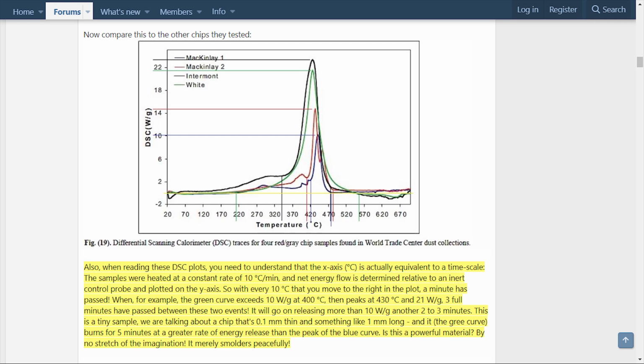So with every 10 C that you move to the right in the plot, a minute has passed. When, for example, the green curve exceeds 10 watts per gram at 400 C, then peaks at 430 C and 21 watts per gram, 3 full minutes have passed between these two events. It will go on releasing more than 10 watts per gram another 2 to 3 minutes. This is a tiny sample. We are talking about a chip that's 0.1 millimeters thin, and something like 1 millimeter long, and the green curve burns for 5 minutes at a greater rate of energy release than the peak of the blue curve. Is this a powerful material? By no stretch of the imagination. It merely smolders peacefully." End quote.